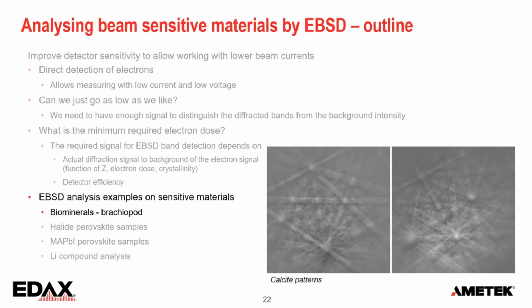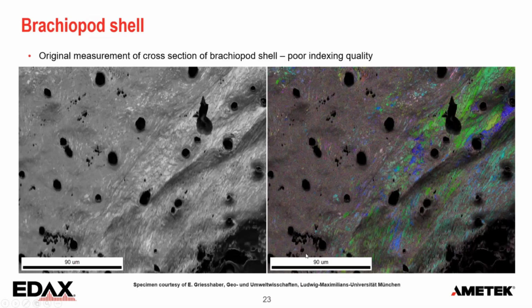Okay, now let's take a look at what that brings us. Let's look at some sensitive materials. The first one I want to display here is a biomineral sample, a brachiopod shell. It's a marine animal, and when you section that, it's a calcite matrix with a lot of organic material in between, which means that you cannot just measure longer or go to higher currents, because it will just fry the organic material, which effectively coats the calcite close to the point of impact, and you lose everything.